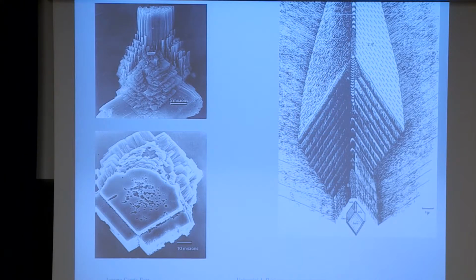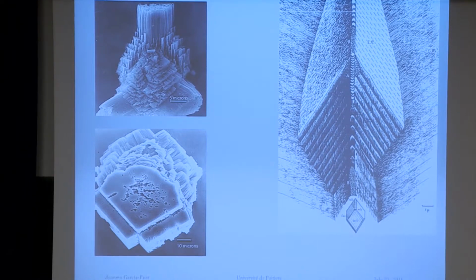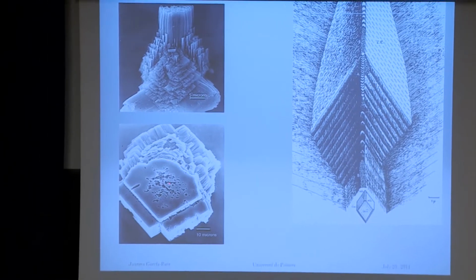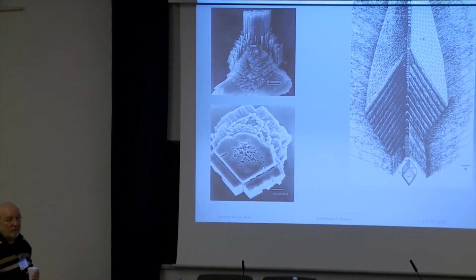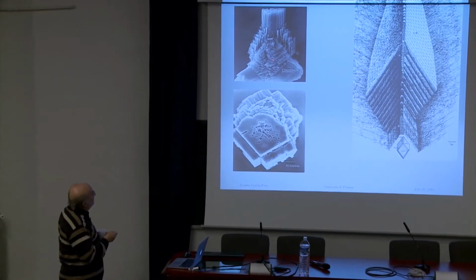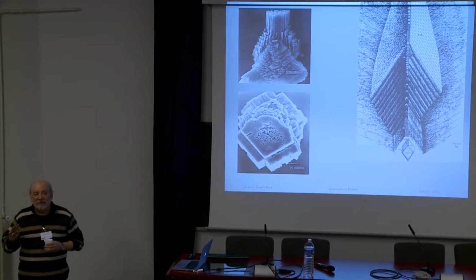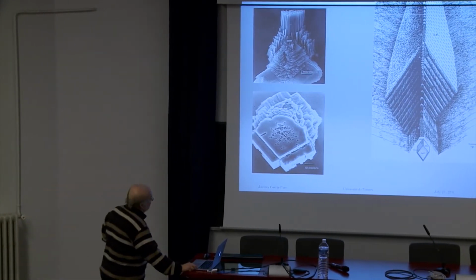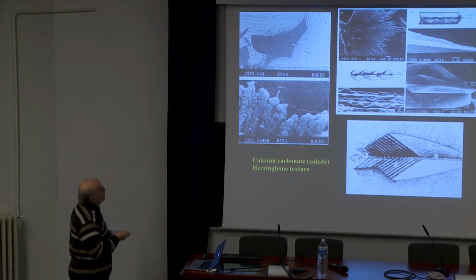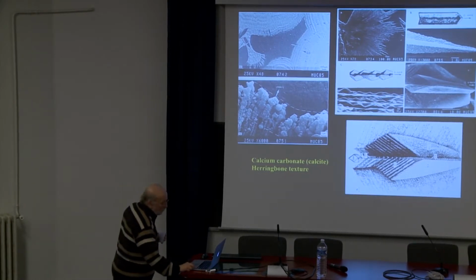And this is what happened with silica. When you perform the precipitation of calcium carbonate in a silica-rich media, high pH, okay, in which you have the first and second deprotonation of the silicic acid, you really stop the typical, the classical growth mechanism by nucleation and spread, or by screw dislocation, to really have nanocrystal formation. Maybe Dennis Eva told you the first day about this, right? So you have a nanocrystal formation, and then the morphology of the initial rhombohedral crystal changes dramatically. This is what we have, completely different morphologies, no more flat faces.